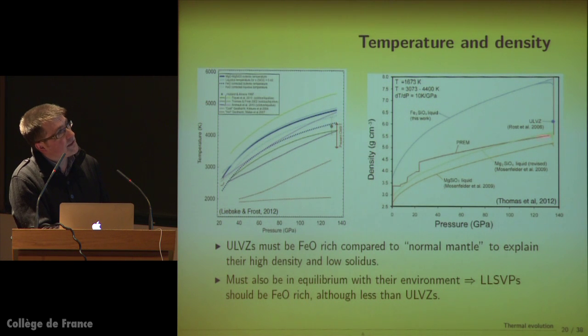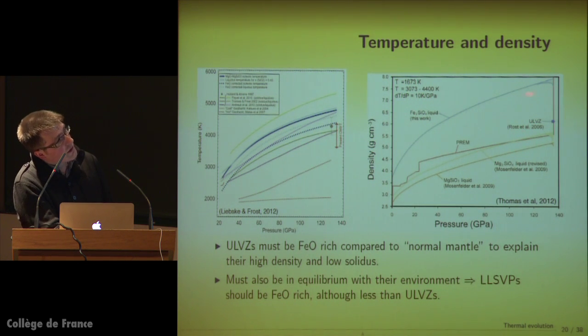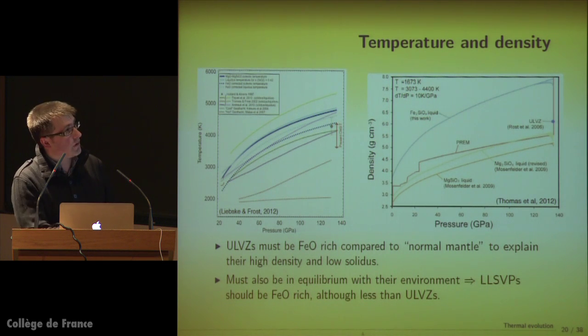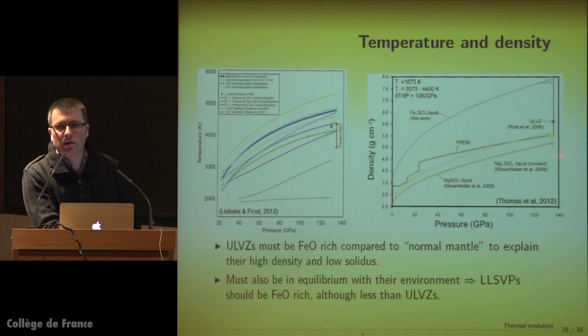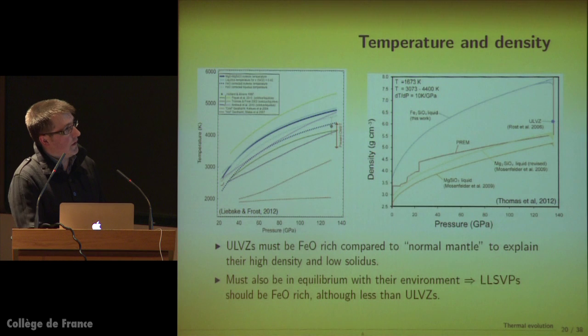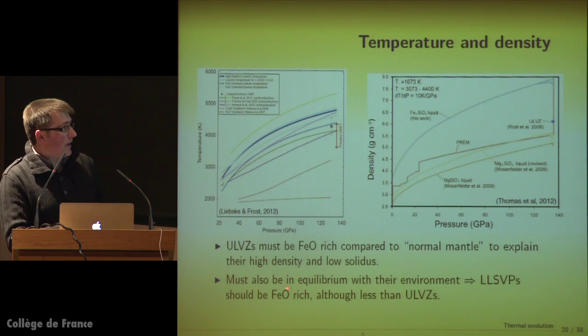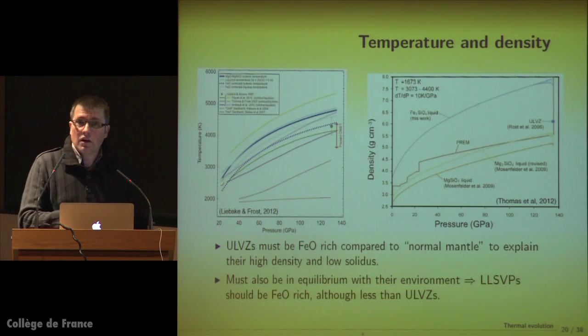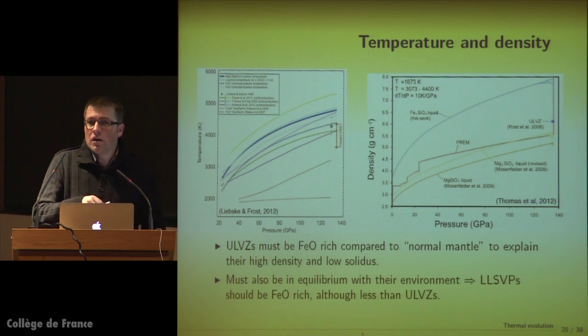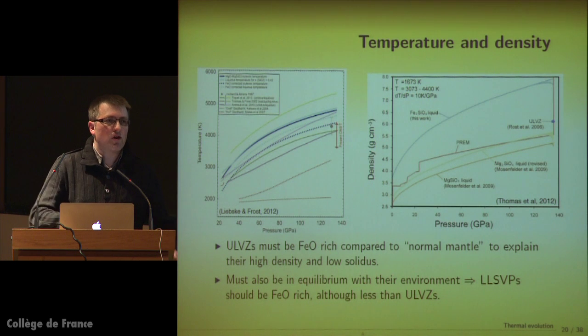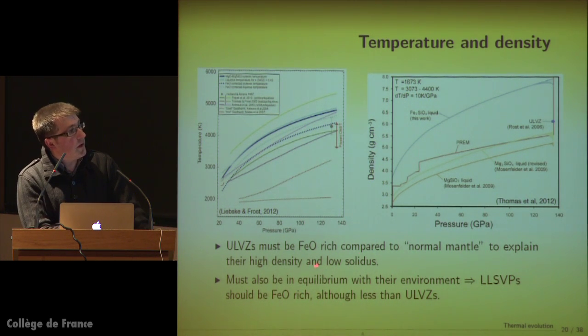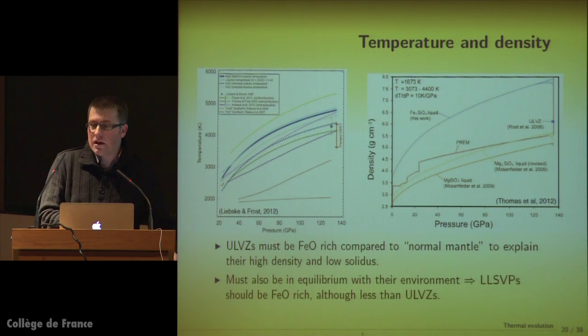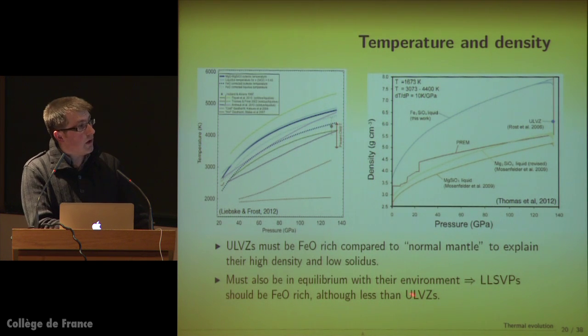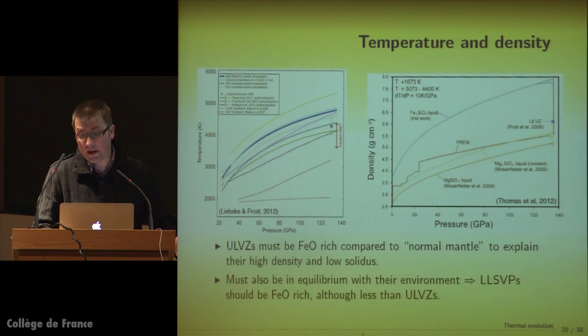Okay. In terms of density, if you want to match the density that I just discussed from Sebastian Rost, you need to mix normal mantle with something that is much more iron-rich, okay? Of course, this number, the actual ULVZ density, is not that well constrained, but there are some constraints, and we need to use them. So this means that ULVZs must be rich in iron compared to normal mantle, but since they are also very tiny patches, maybe not a big chunk of stuff, there must be equilibrium, and particularly if it's liquid, if it's partial melting, it should be in equilibrium with the surroundings. So the big LLSVPs must also be rich in iron, although less than the ULVZs.